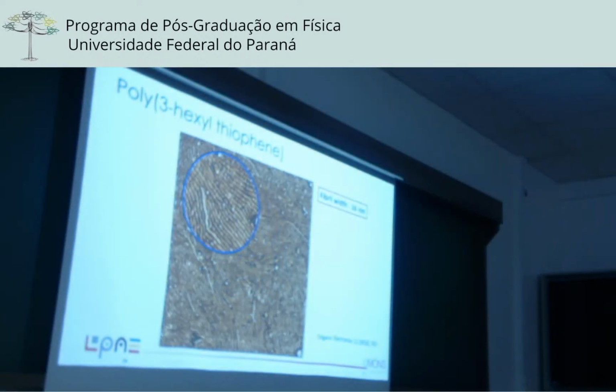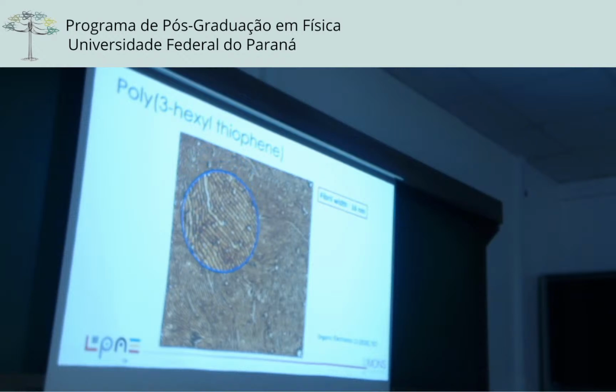So we played with hundreds of different systems coming from Europe, from the US, from Japan, from Australia, and we always find that with pi stacking, it's possible to have these nanofibers. And one that is extremely interesting is poly-3-hexylthiophene, P3HT, and you clearly see here very nice fibers of 16 nanometers, corresponding to the length of the molecule. So also for P3HT, we have this pi stacking information.